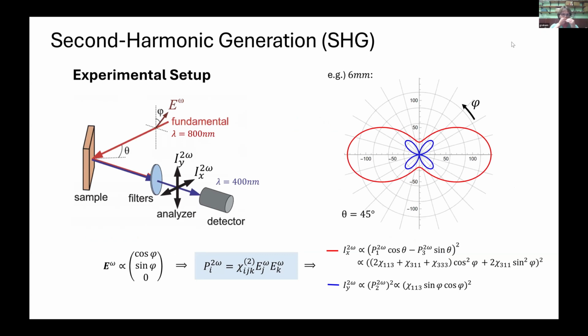But experimentally, how we do this is fairly simple. We have a 800 nanometer pulsed laser polarized at angle phi. We hit our sample and we collect the second harmonic light polarized along either the X or the Y direction, and then we sweep our incident polarization while measuring intensity. And that's what gives us these polar plots. So this right here is just a theoretical calculation. I go in and I apply the symmetry operations of the 6mm point group, so the 6-fold axis and these 2 mirror planes. And it gives me selection rules on my tensor that give me this unique polarimetry, so I can know what to expect.